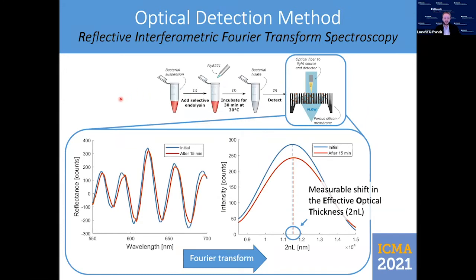Here is an example of the optical spectra before and after 15 minutes of the bacterial lysate filtration. The targeted bacteria was thus the Bacillus cereus with an initial concentration of 10 to the power 6 colony forming units per mil. After 15 minutes, there is a change in the optical spectrum that we can see. And when we apply a Fourier transform, we can see that there is a very small change in the so-called effective optical thickness, which is this 2NL factor, where N is the refractive index of the whole compound of the membrane here, and L is the length traveled by the light through the membrane and back.